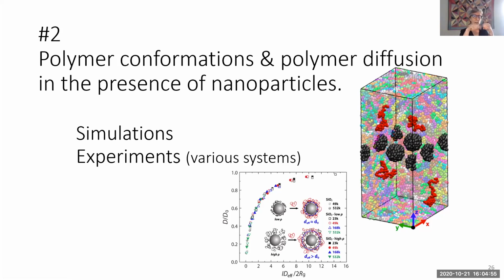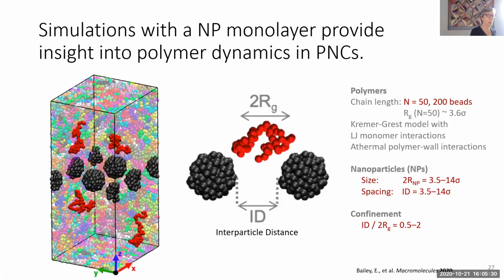So now we can compare the diffusion really right between two particles, where things are going to be very distorted chain conformations and missing entanglements and stuff like that. But we can also see, as we go further and further away from these nanoparticles, how far that behavior persists away from the particles. And so I think of this as the princess and the pea experiment. Obviously, if you're right on top of the pea, you're going to feel it. But if you're further away, like 10 mattresses away, as the fairy tale goes, will you still know that there are particles there? And so again, we'll start with the simulations and then we'll go to the experiments.